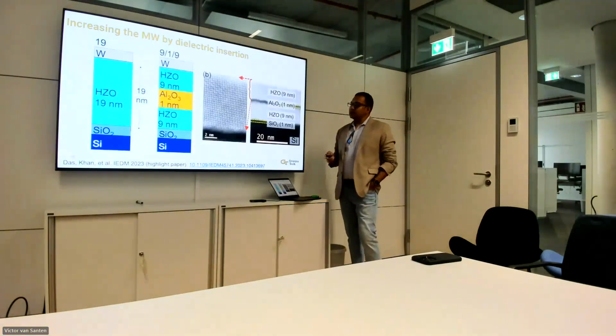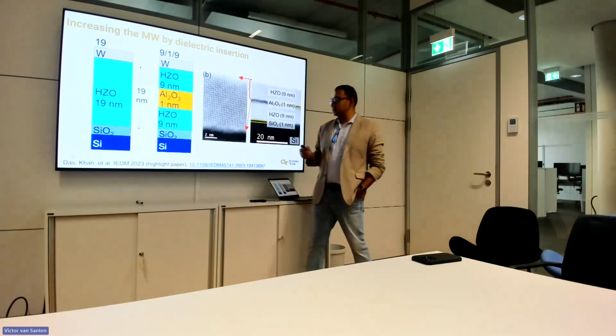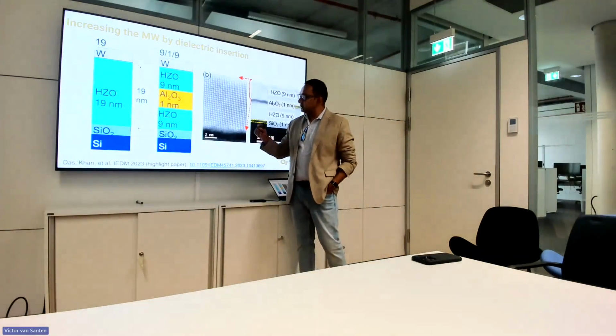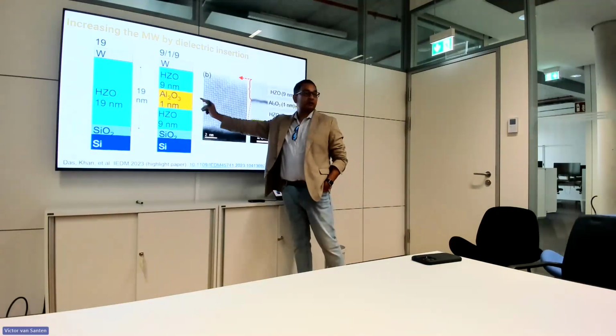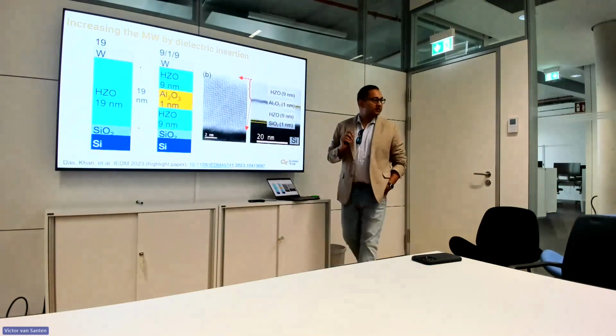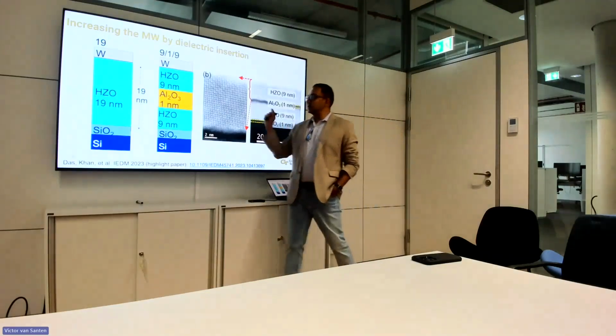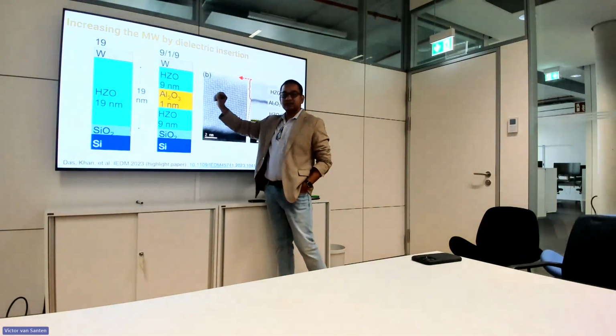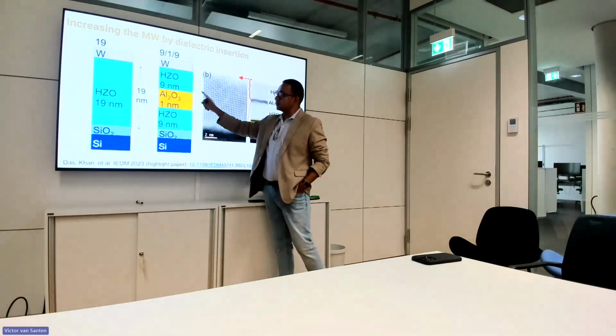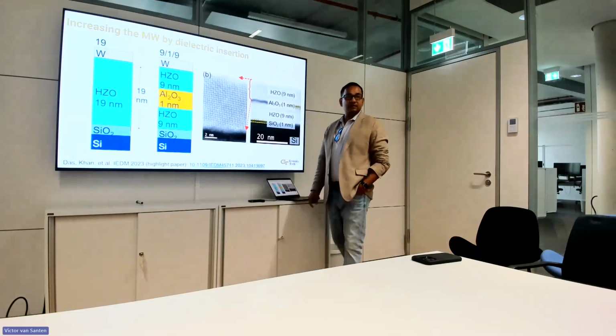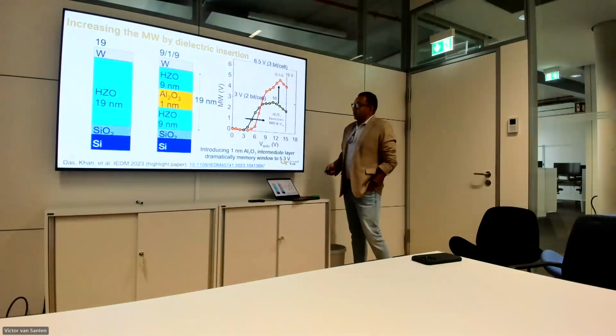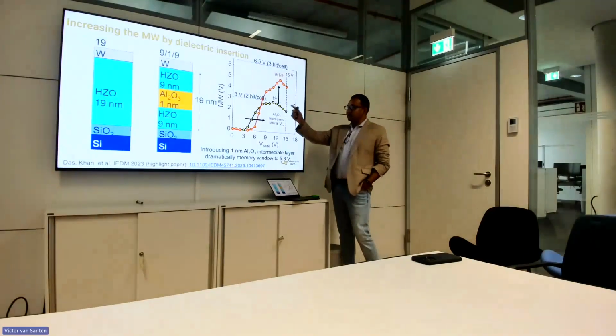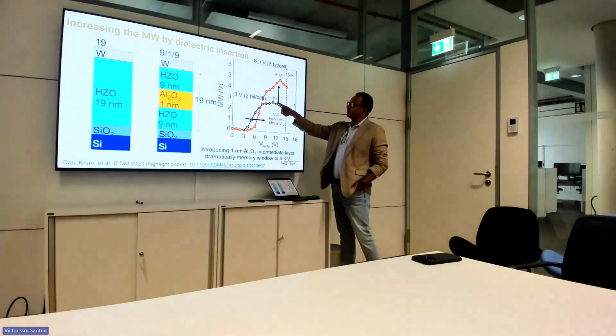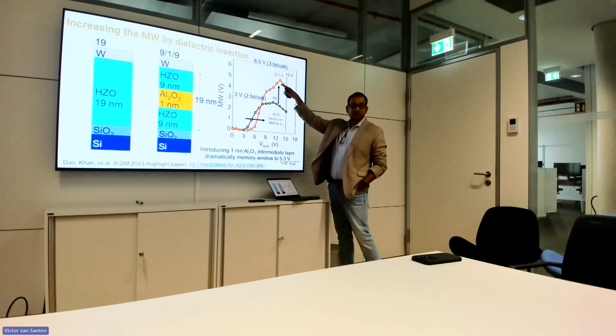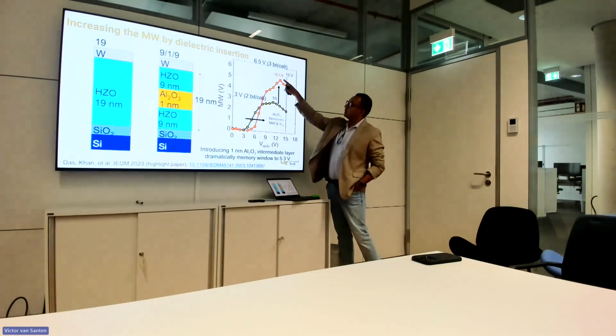Okay. So then what we did was, at that time, my postdoc, Dipjyoti Dash, inserted a 1 nanometer layer. So remember that our total thickness budget is 19 nanometers. So we inserted 1 nanometer and reduced the HZO thickness a little bit. So 9 plus 9 plus 1 is 19 nanometers. So basically the total stack thickness remains 19 nanometers. And then what we could clearly see is that as we insert 1 nanometer of aluminum oxide, the maximum memory window actually jumps up by almost 60% to around 5.5 volts.